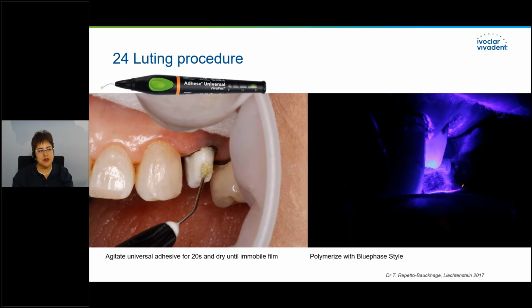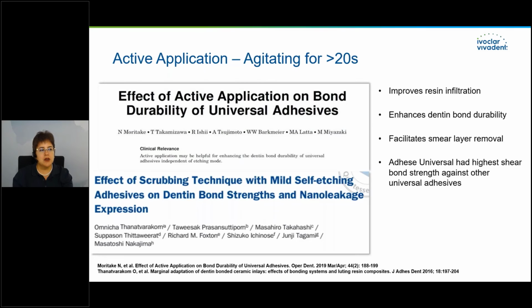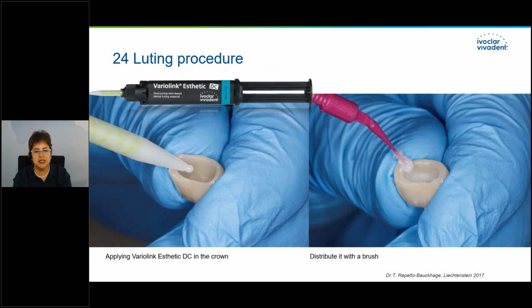And I love this delivery way because you have no waste, and you have a very low film thickness of 10 microns. And because it's a light-cure adhesive, it needs to be polymerized. And here you can see a study from Moritake. In 2018, he suggested that agitating for 20 seconds will give very good resin infiltration in the dental tubules, and with the polymerization, you will have a good hybrid layer. And this will, of course, also increase the high bond strength compared to other universal adhesives.